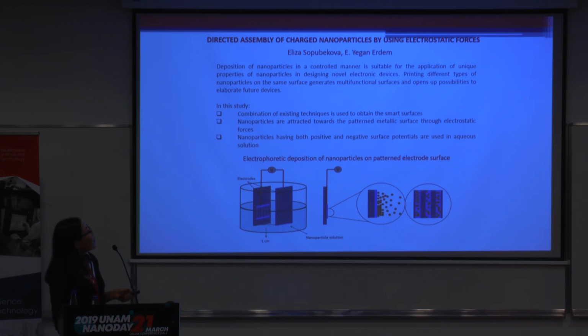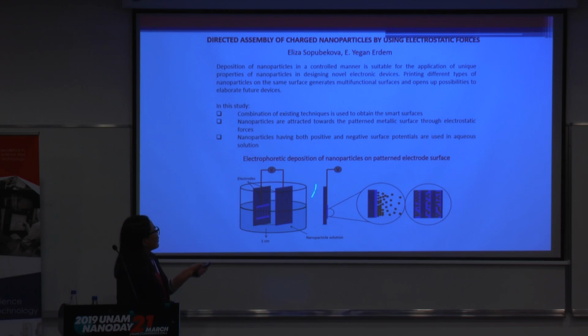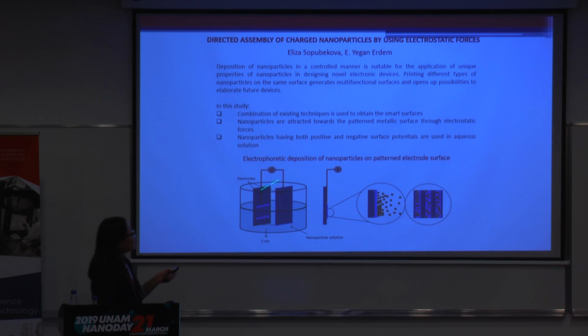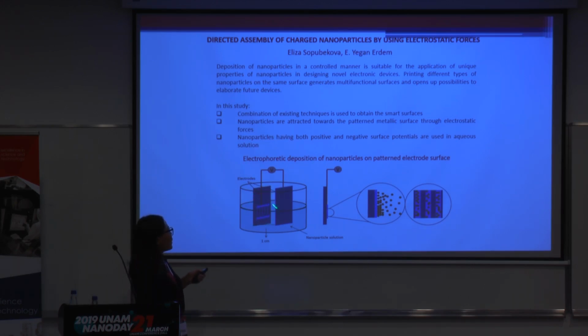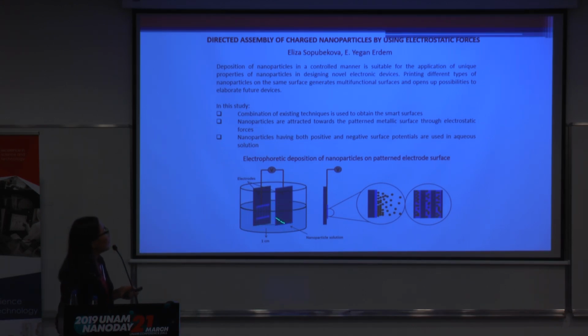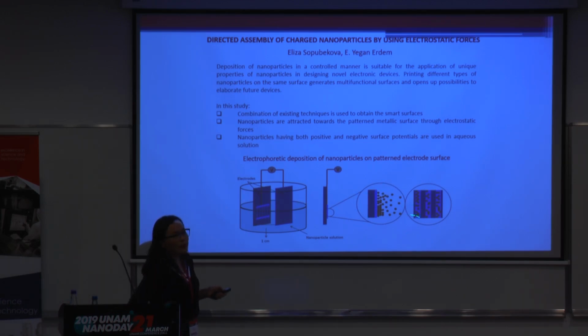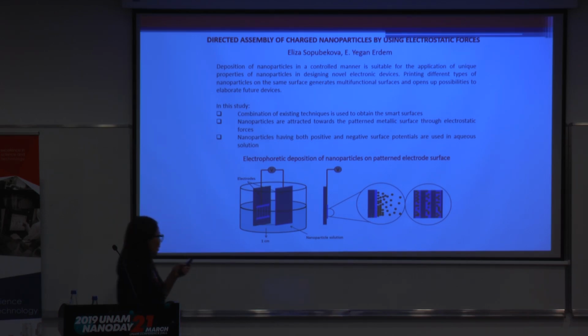In this project, we used electrophoretic deposition method to obtain this nanoparticle pattern. So we have these two electrodes, and the working electrode has patterned metallic electrodes. And when potential is applied between these electrodes, an electric field is generated between them, and charged nanoparticles are attracted towards the opposite potential electrode surface. So that's how particle patterns obtain the geometry of the electrodes.